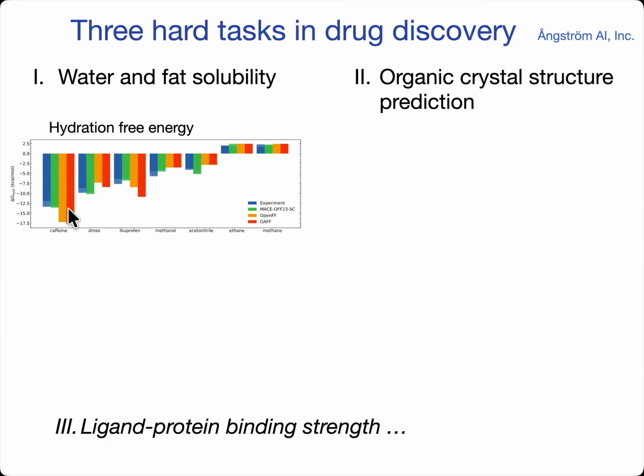So here's an early example of a MACE model fitted to a set of small molecules, nothing to do with solubility. It's just molecules in vacuum. It was called the SPICE dataset, and MACE-OFF was the first model we made. And then we calculate the hydration-free energy. So big box of water, alchemical transformation, and you get the experimental result back, basically. So blue is experiment, green is the model. And empirical force fields don't typically do super well in this task, even though they've been fitted to solubility data. These are 2 standard models.